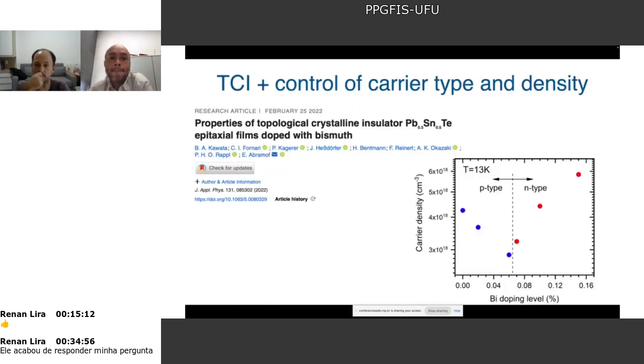Okay, and one point that was discussed in those published papers is the effect of carrier density. When you increase the tin concentration to go from trivial to topological phase, you also increase the carrier concentration because of the growth. It's something you cannot control. So what we want to do now is to control carrier concentration and carrier type while keeping the topological phase. So we are using these samples doped with bismuth. And with bismuth, you can go from p-type to n-type, and you can decrease carrier concentration and also increase it in the other type. So we want to study this.